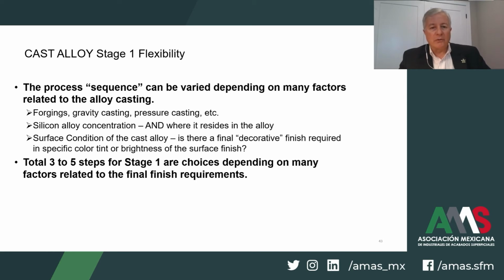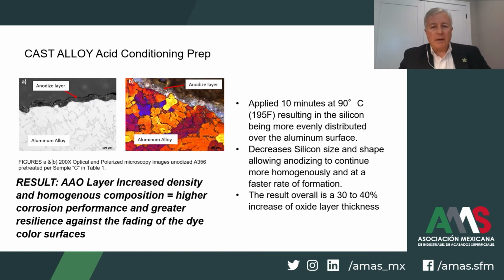For more focus on the functional anodizing applications, those that don't require high brightness, high color surface finishing, we have fewer steps required in stage 1. But where there's a greater focus on decorative appearance, performance related to decorative appearance, we have more steps required for stage 1 processing. The right surface preparation choice becomes very critical to account for the silicon in the alloy.